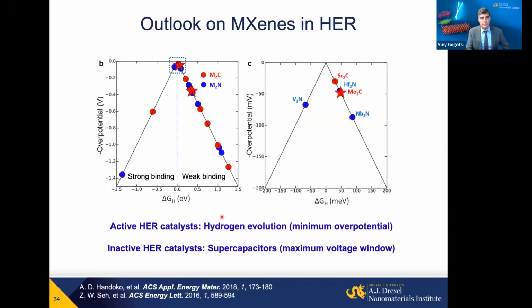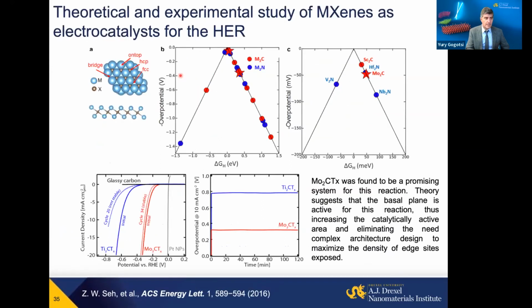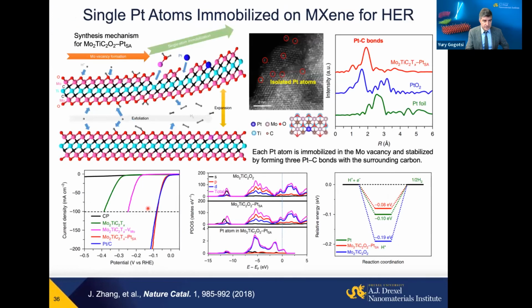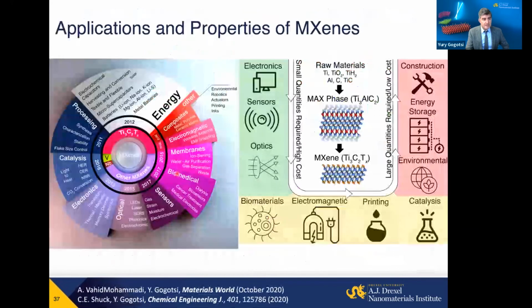They can be used for production of hydrogen as electrocatalysts. Some of them have been shown to be close to platinum by DFT calculations here. But experimentally, they have been shown to actually be very competitive to molybdenum disulfide and other materials here. And they also can be used as support for catalysts, for example, again, for water splitting, for single platinum atom catalyst design. There are many, many other applications here, but I want to leave a few minutes for questions.